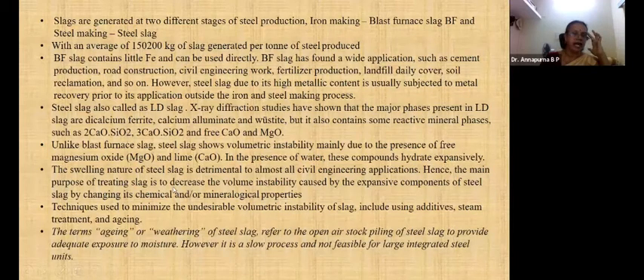Hence, the main purpose of treating slag is to decrease the volume instability, because we have to reduce the magnesium oxide and lime, which is the main criterion. Techniques used to minimize this undesirable volumetric instability include using additives, steam treatment, and aging. Aging or weathering of steel slag refers to open-air stockpiling of steel slag to provide adequate exposure to moisture. This reduces the content responsible for volumetric expansion. But it is a very slow process and not feasible for large integrated steel units.